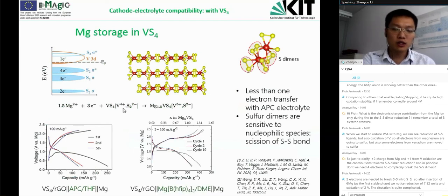But if we switch to this borate electrolyte, we have much improved capacity, and also we have a very nice plateau. A possible reason could be that the sulfur dimer we have in this VS4 structure is quite sensitive to nucleophilic species. So if it's coupled with the APC electrolyte, then we have the breaking of the sulfur-sulfur bond, so of course we have a relatively lower capacity.